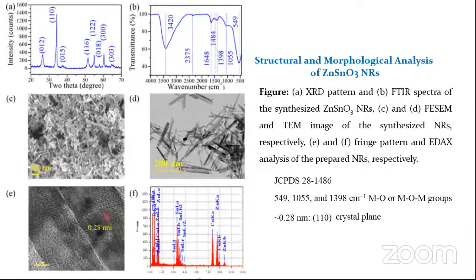So this is the structural and morphological analysis of the zinc stannate nanorod. All the XRD and FTIR clearly reveal that the zinc stannate nanorod is formed in the synthesis procedure. As you can see here, in the SEM image, the zinc stannate nanoparticles are rod-like in shape. To further prove the formation of zinc stannate nanorod, we have taken the fringe pattern. The fringe distance is 0.28 nanometer, which represents the 110 crystal plane of the zinc stannate nanorod.